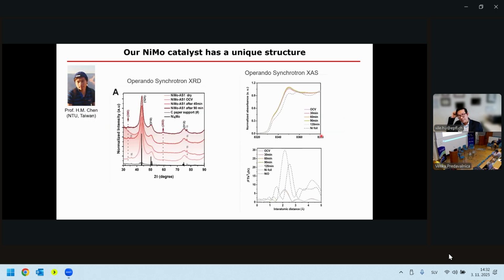Again, we're trying to understand it by operando X-ray absorption spectroscopy as well as operando synchrotron XRD. And again, thanks to our friend in Taiwan, Hao Ming Chen, we are able to do it. So here I show you some data. You can see that we compare different states under operando potential to reference compounds that we know, like the catalyst, which is nickel 4 molybdenum in terms of the structure. We also look at XAS, both XANES, pre-edge, as well as EXAFS structure on both nickel and molybdenum, and so we are able to deduce its structure, and I will show you the structure.